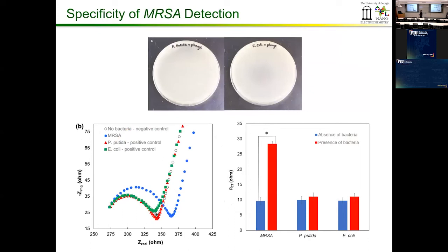Another specificity test with MRSA. MRSA is another pathogen, like I mentioned, and here it's much more pronounced. The no bacteria case versus the non-target pathogens such as Pseudomonas and E. coli are all sort of overlapping, but when you have your target pathogen, you can see a clear distinction in the impedance. You can also see it here. In the presence of MRSA, you can see a significant impedance change, and then in the absence of MRSA, there's nothing. And you can see with other bacteria, there's not much change between no bacteria and the bacteria case. Which means that the electrode is selective towards MRSA detection.